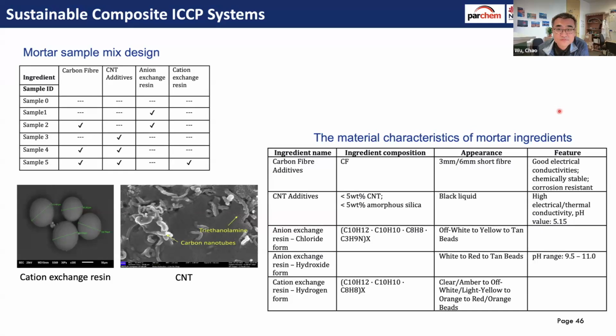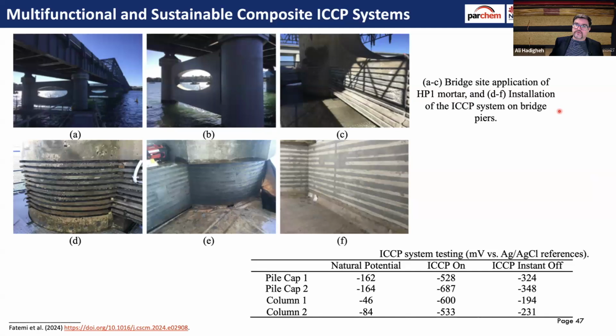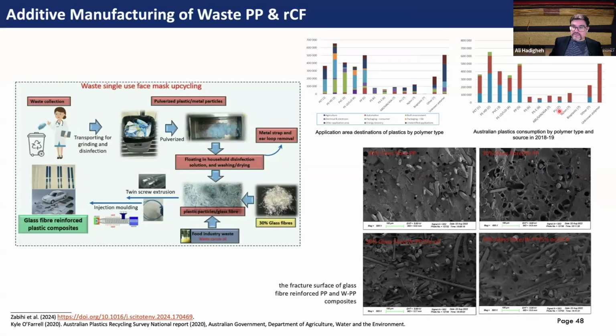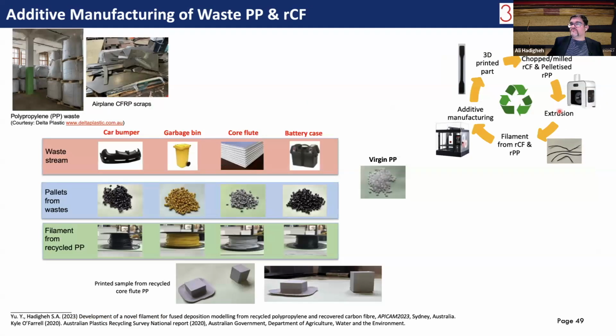Thank you. So the conductivity is extremely important in this case, because you are doing ionic conductivity between the environment and electronic conductivity. So now we are using these recycled carbon fibers within these mortars to improve the conductivity and install it onto a bridge for cathodic protection. The other type of applications that we have been doing within the group was incorporation of carbon fiber or glass fiber inside filaments for 3D printing.